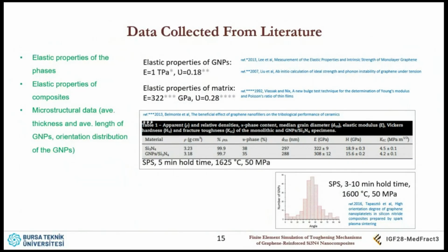Okay. So I also collected some other data from the literature, like the elastic properties of graphene. Likewise, that of the matrix. And some other microstructural data like thickness and average length of graphene nanoplatelets. So average length was found as 2 micrometers, average thickness about 10, 15 nanometers.